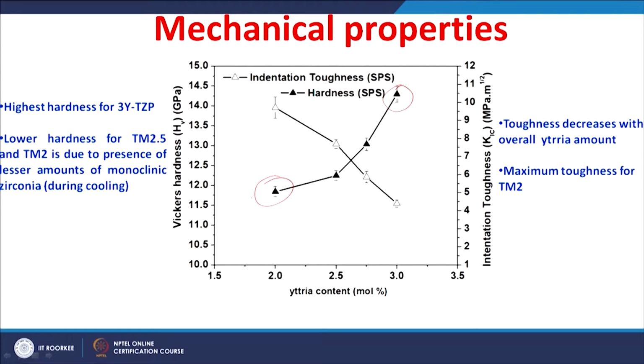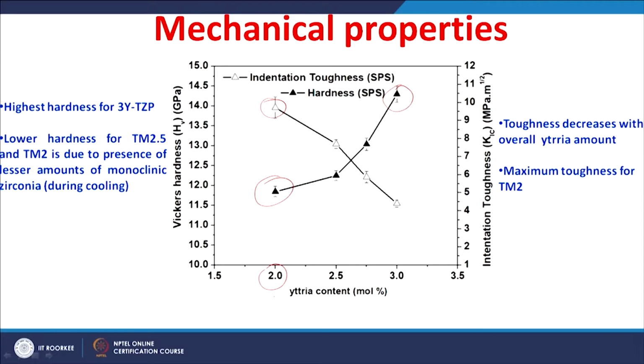With respect to toughness, the fracture toughness again varies from around 3.9 MPa root meter to around 9.5 MPa root meter with the yttria content. The maximum toughness is obtained for the ceramic stabilized with the minimum amount of 2 mole percent of yttria, whereas the hardness obtained is lower for that having lower yttria content, probably due to the presence of lesser amounts of monoclinic zirconia that may form during the sintering. So, a higher hardness of around 14.5 gigapascal and a fracture toughness of around 9.5 MPa root meter, a combination can be obtained by changing the yttria content.